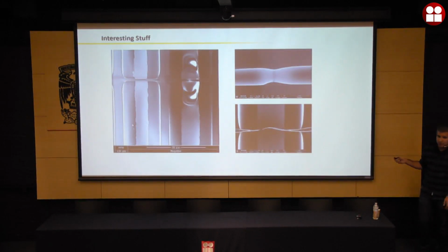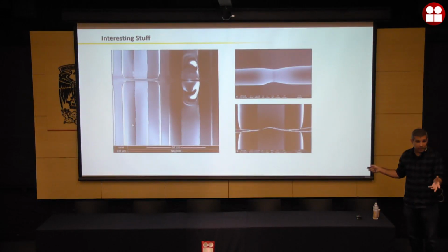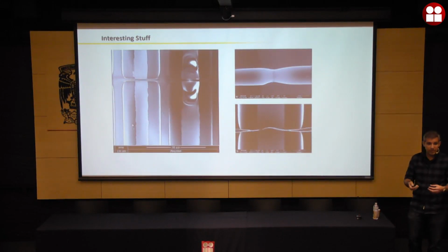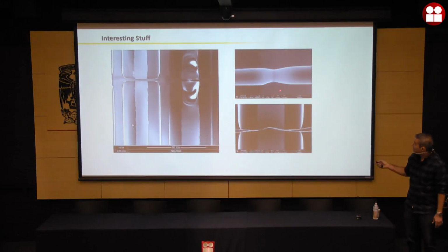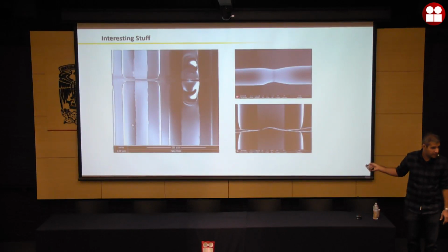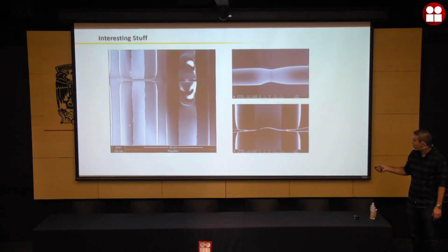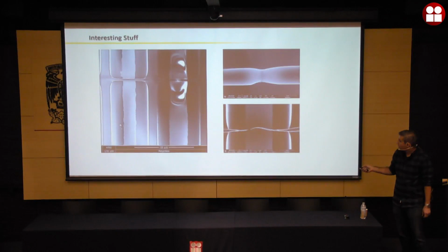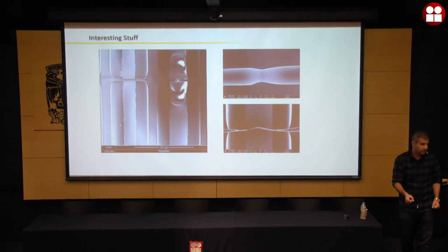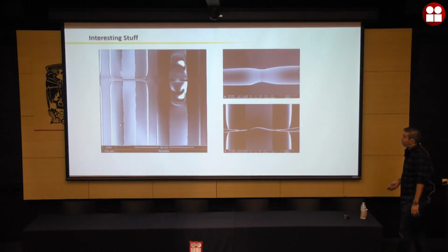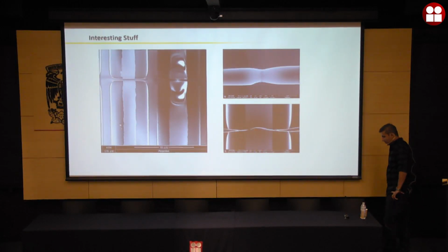The second thing is that if you do the same process in air, you probably see something like this. Because you change the convection properties of the system, the glass silicon dioxide cannot sublimate, and it only melts down and breaches. And if you suddenly increase the voltage, you create this funky shape, which is basically like I apply 60 volts immediately to the microfiber, and it just bursts everything. So these are interesting phenomena that we observed on the nanofiber gaps.